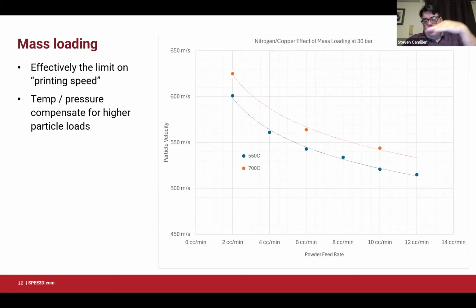And of course, it does seem to be asymptotic. So it seems like at some point we can just keep increasing the particle loading if we don't mind the pressure being lower than it might be otherwise. So the short answer here, for those of you that haven't worked this out yet, is if you really want to get the highest possible velocity out of your powder, just inject a very small amount of it into your process and you'll be able to observe the highest cold spray velocity.